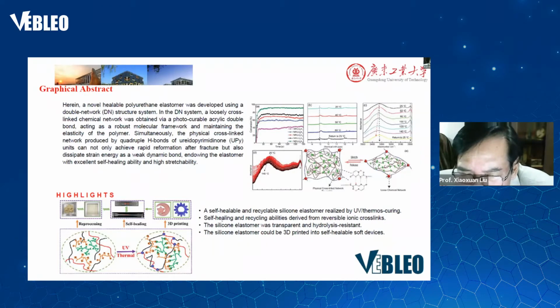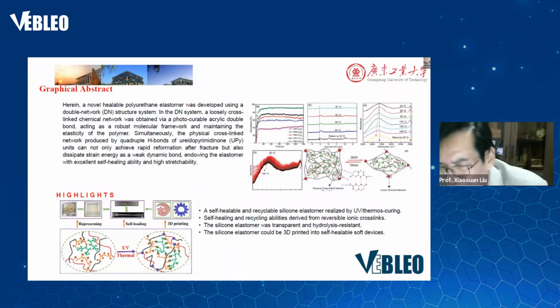And the self-healing and recycling abilities derive from reversible ionic cross-linking. The silicone elastomer also shows apparent hydrolysis resistance. The silicone elastomer could be three-dimensionally printed into self-healable soft devices.